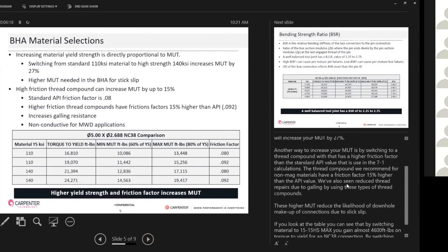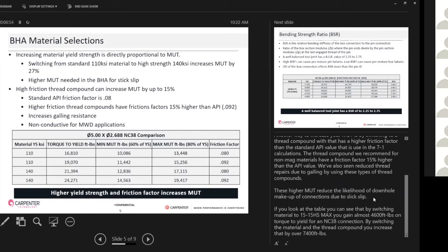Another easy way to increase your makeup torque is by switching to a thread compound that has a higher friction factor. And the standard API friction factor is 0.08. We recommend the thread compound for non-mag materials have a higher friction factor that's 15% above API. We also see a lot less thread repairs and reduced galling due to these thread compounds. And the higher makeup torque reduces the likelihood of downhole makeup or connection movement downhole due to stick slip.